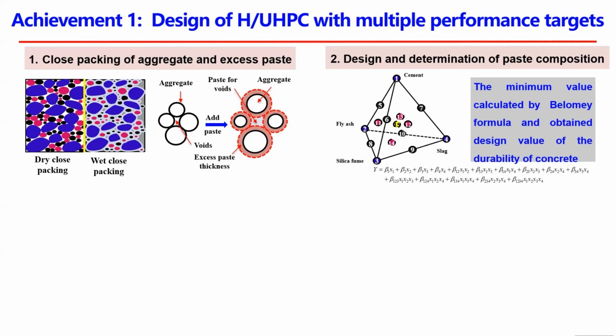Third, we come to the binder composition. Before, people just seemed to choose them randomly or just based on literature. Here we propose to use factorial design, and I give you an example here. Like if the binder consists of four components, like cement, fly ash, silica fume, and slag, and use this method and approach, then we could establish the mathematical relationship between the properties or quantitative microstructure parameters. Basically, anything that can be quantitatively described with the composition of the binder.